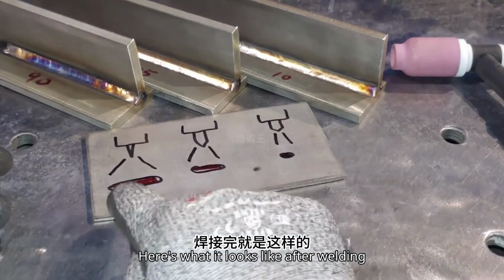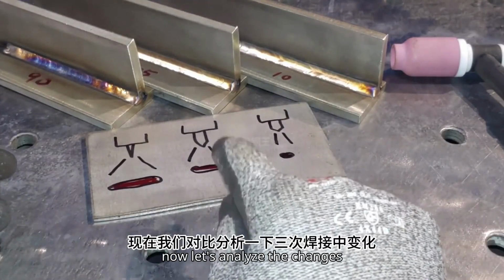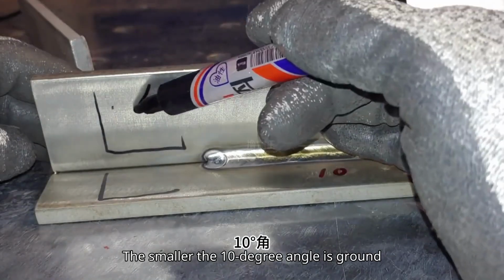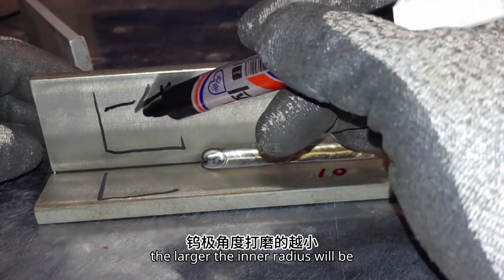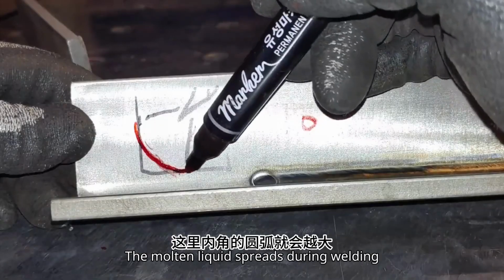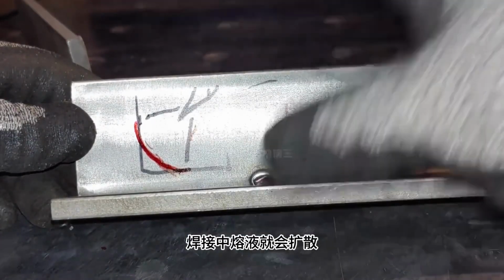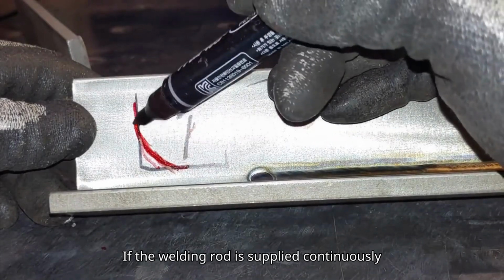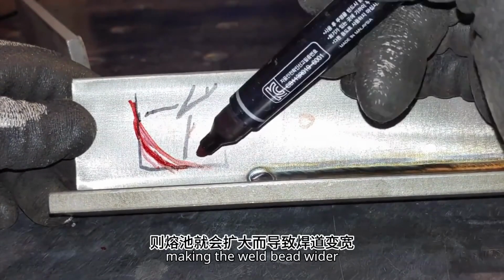Here's what it looks like after welding. Now let's analyze the changes from the 3 welds. The smaller the tungsten electrode angle is ground, the larger the inner radius will be. The molten liquid spreads during welding. If the welding rod is supplied continuously, the weld pool expands, making the weld bead wider.